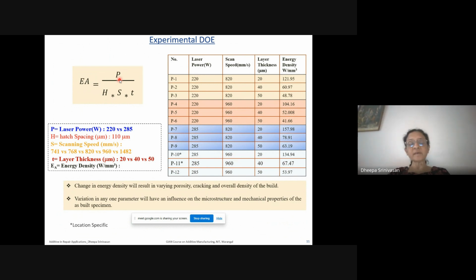Now, sometimes in additive manufacturing, and there is lots of literature as well on Inconel 718 and a few other materials, where people have tried hipping. And the hipping, particularly for additive, because it's a very rapid solidification process, sometimes results in segregation of elements. So not always is the energy density that is fine tuned conducive, even if it is a dense part optically. It may or may not give the necessary properties and long term stability.